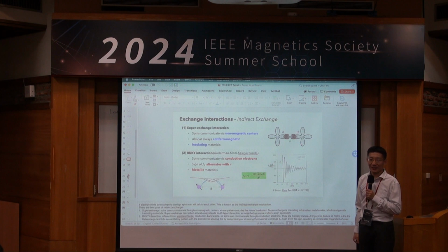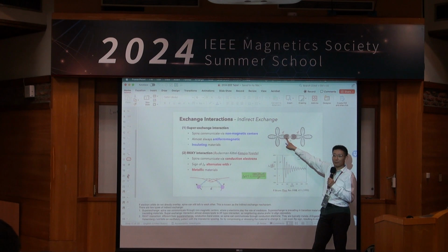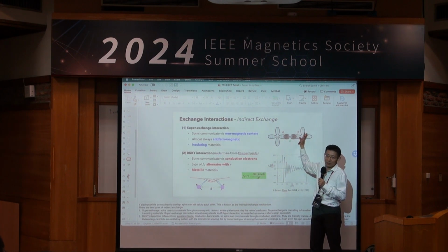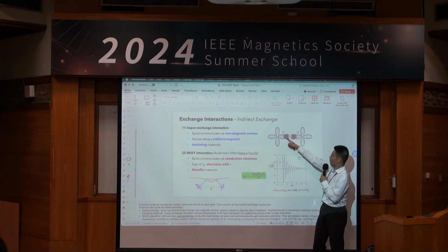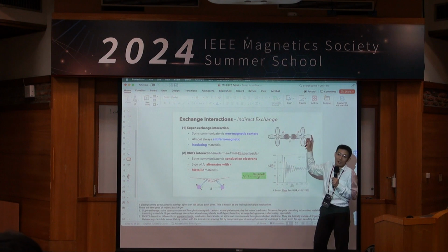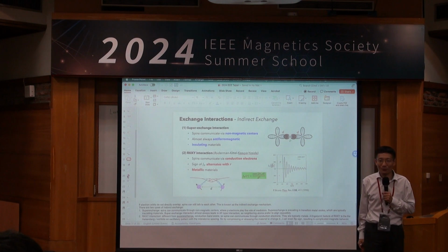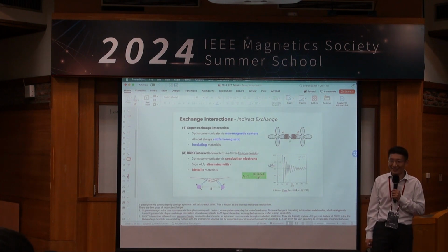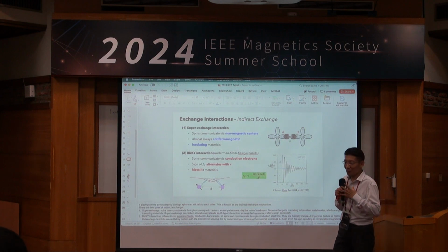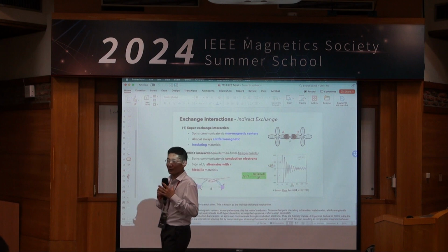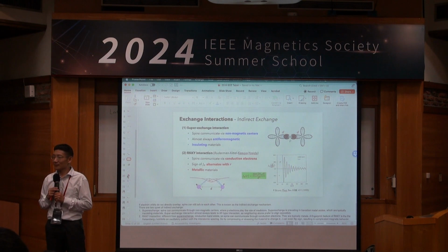Okay. Thank you. For example, in some materials you have a strong spin-orbit coupling here, but the bond angle is zero. Still, you do not have DMI. And in some materials, the bond is highly twisted, but the spin-orbit coupling is too weak. Then the DMI interaction is negligible. Two conditions. And sometimes the two conditions are not independent, because the spin-orbit coupling is somehow locally induced by the broken inversion symmetry. So, yeah. Any other questions?